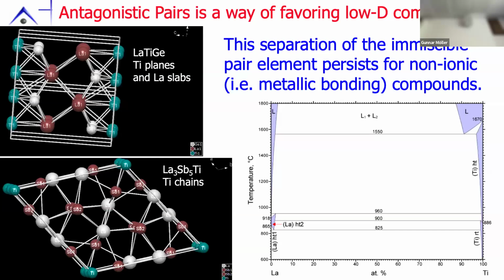Here you have the lanthanum titanium binary phase diagram. There are very few, I think these are the two known ternary compounds. Lanthanum titanium germanium has the germanium separating titanium into sheets, lanthanum into slabs, a two-dimensional motif. Okay, lanthanum 3 antimony 5 titanium, the antimony sheathes the titanium into one-dimensional chains. So by segregating these unhappy pairs, you actually have a recipe for creating low-dimensional structures.